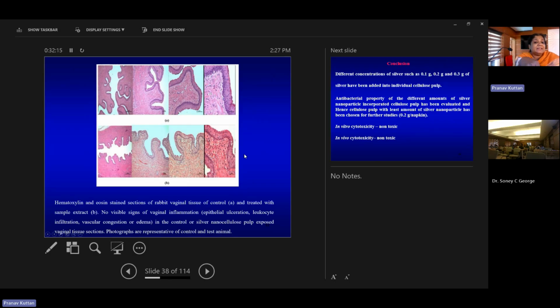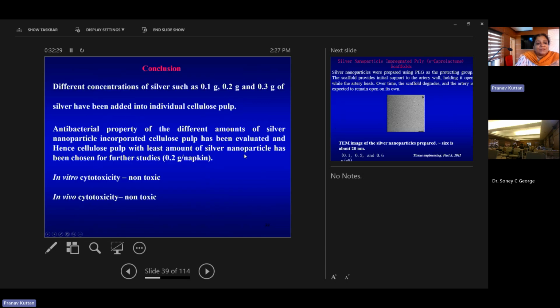A and B are the rabbit's vaginal skin, with the control and with the silver nanoparticle, and both have the same pattern, indicating that there is no irritation caused to the vaginal cell lines. So the conclusion is different concentrations of silver such as 0.1 gram, 0.2 gram and 0.3 gram of silver were added to this cellulose pulp, and the antibacterial activity of the different amounts of silver incorporated cellulose pulp was evaluated, and the least amount of silver, that is 0.2 gram,